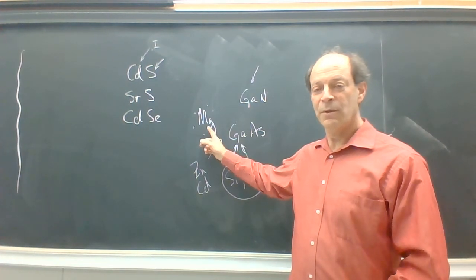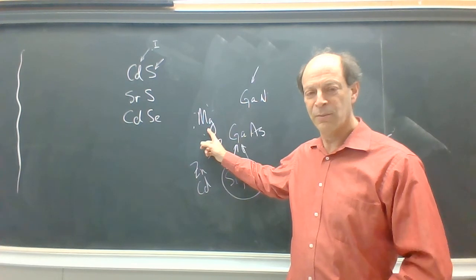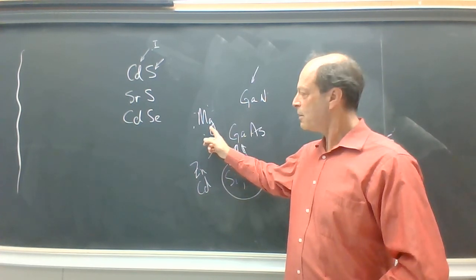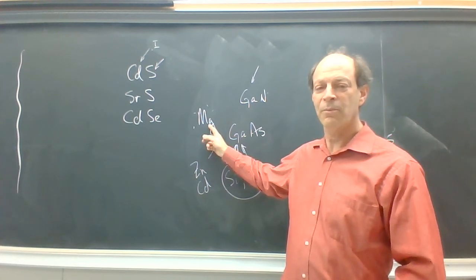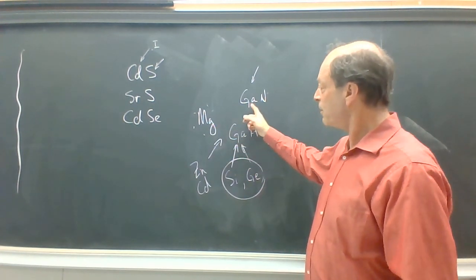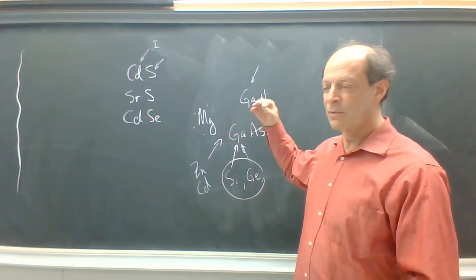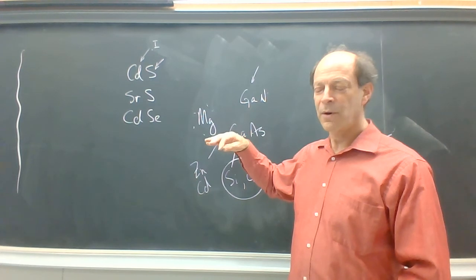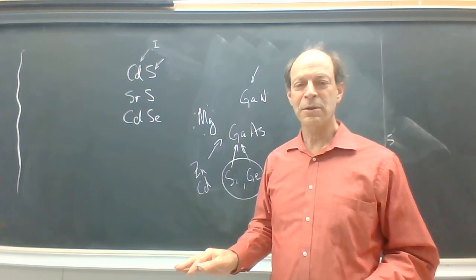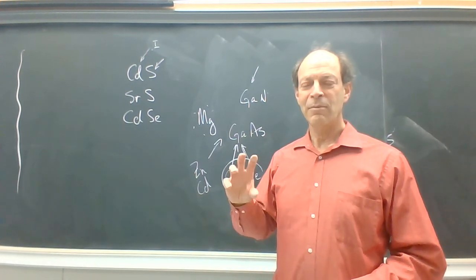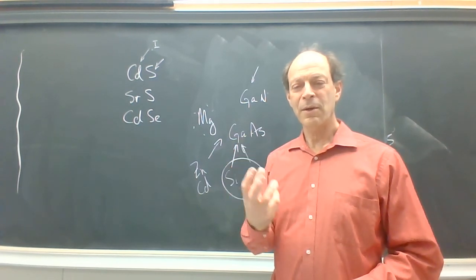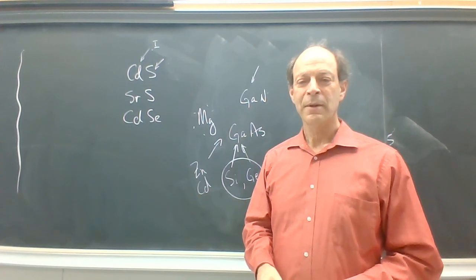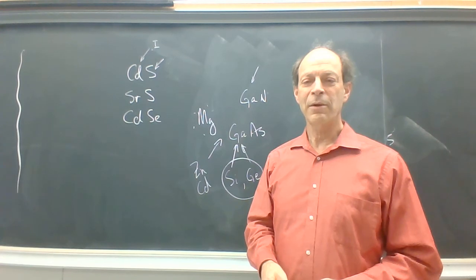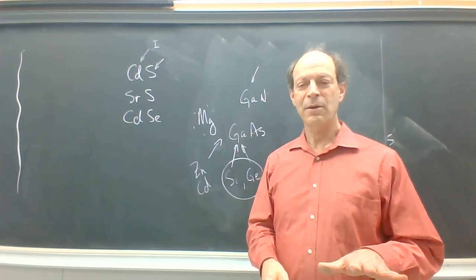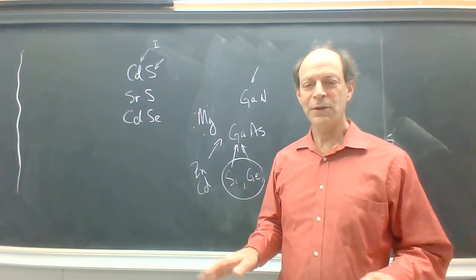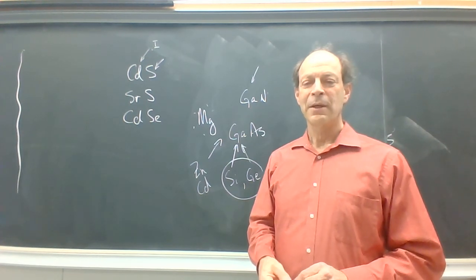Nevertheless, magnesium turns out to be able to accommodate to that tetrahedral bonding symmetry, provided you heat the crystal containing the magnesium impurity to a sufficiently high temperature, and people weren't aware of that. So it was found that if you substitute magnesium into gallium nitride and you heat that doped material up to approximately 900 Celsius, which is extremely high in temperature for most 3,5 semiconductors, that magnesium can, in fact, accommodate to the gallium site and produce a hole. Now, that was a major achievement. It's not capable of very high doping concentrations. It's limited in the 10 to the 16, 10 to the 17 per cubic centimeter range, but sufficient for a good LED. So that was one breakthrough.